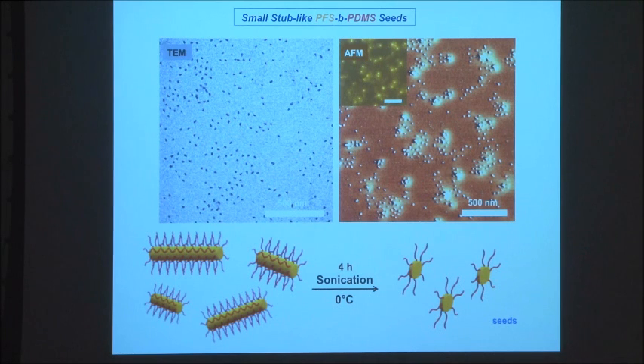So you take the block copolymer, dissolve it in THF, which is a good solvent for both blocks. You add hexanes very slowly. This generates cylinders of different length because it's a self-nucleation process. The cylinders don't start growing at the same instant. So you get cylinders of different size. You can sonicate these down using a powerful sonicator to give you very small seeds, which you can see here, which will represent in this cartoon.